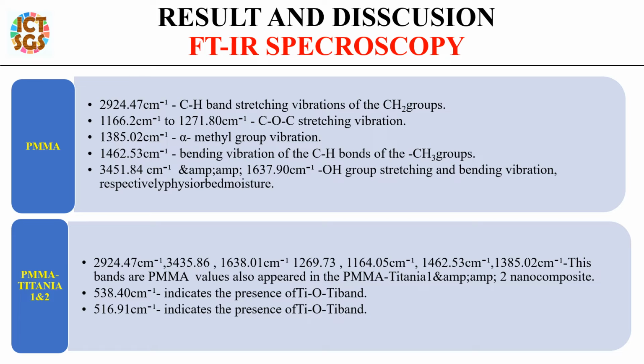3451 per centimeter and 1637.90 per centimeter are the O–H group stretching vibration and bending vibration respectively, from physiosorbed moisture, and another in the PMMA-Titania nanocomposites. The above PMMA bands also appeared in these composites. Two additional bands also appeared in these composites.